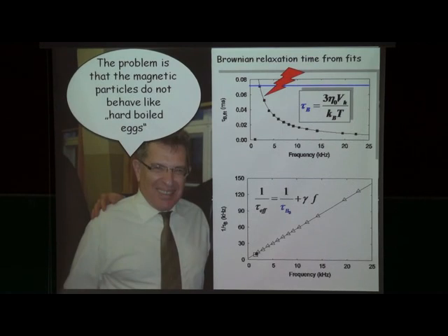The effective Brownian relaxation time is some geometric, or this kind of fixed relaxation time, times a factor gamma and the driving frequency. So you have a very quantitative functional dependence between driving frequency and an effective Brownian relaxation time.